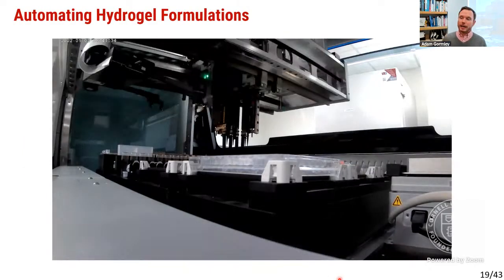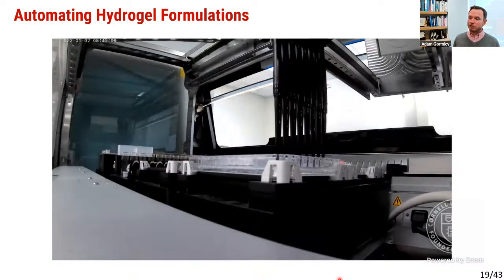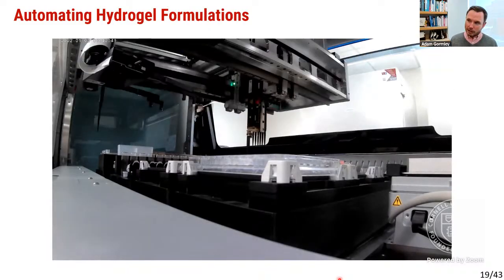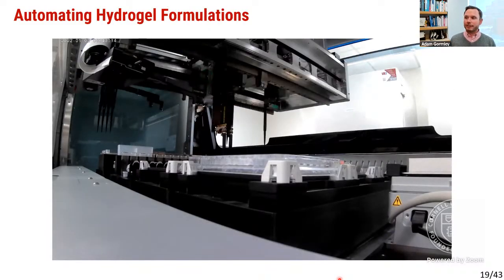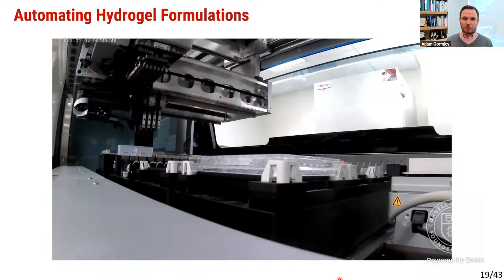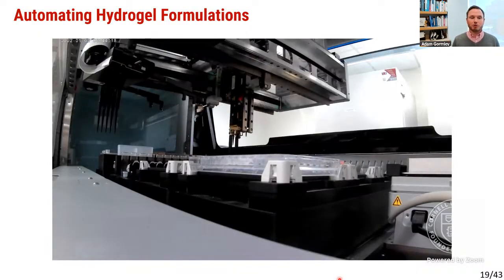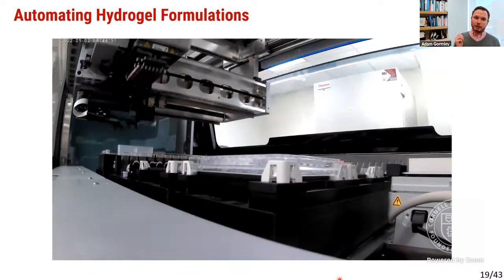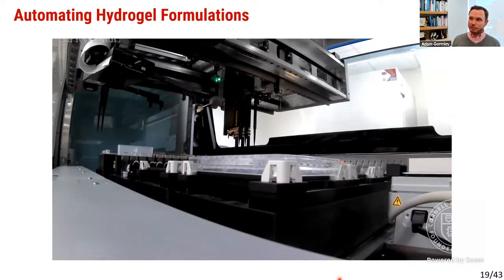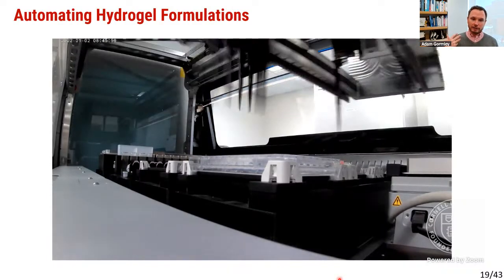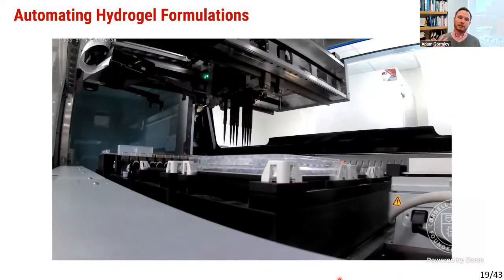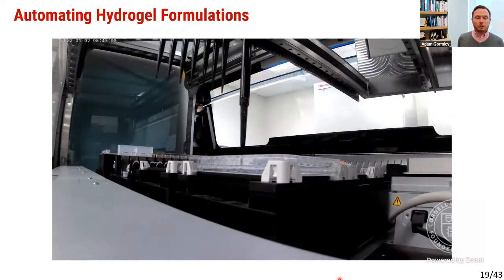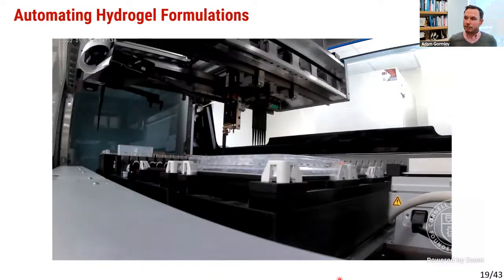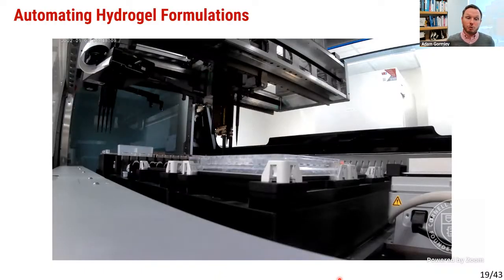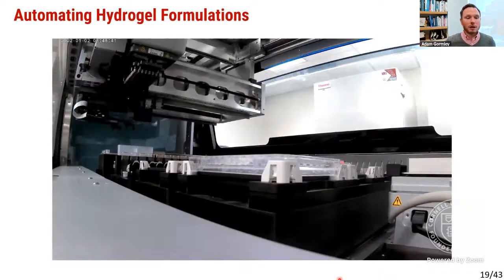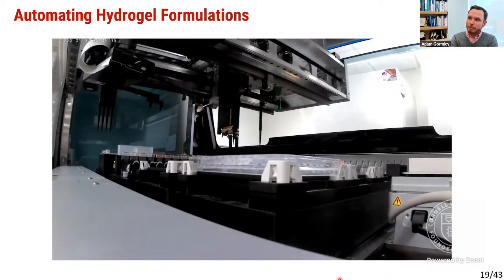Now, one of the challenges we had to overcome to make this project possible was viscosity. Liquid handling is really great when your solution is just water or DMSO or methanol. But the moment you've got a viscous sample, like a typical polymer used in hydrogels, it becomes very difficult to reliably aspirate and dispense. So we spent a lot of time figuring out the liquid handling parameters to be able to do automated hydrogel preparation. All of that is heavily documented in the paper.